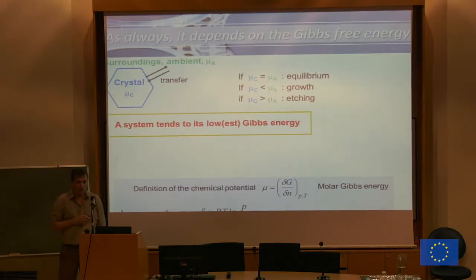Now, how does growth work? It is very simple. It works with the Gibbs free energy or this chemical potential. So we have a reactor ambient where you have certain pressure, temperature, vapor phases of the gases, and you have your crystal. Now, if the chemical potential of your crystal is lower than the one of the ambient, you will have growth. It is that easy. That's all I wanted to say. If you understand that, that's how it works. Now, also the opposite way, if you manage to make the potential of your crystal higher than the ambient, it will also start etching.